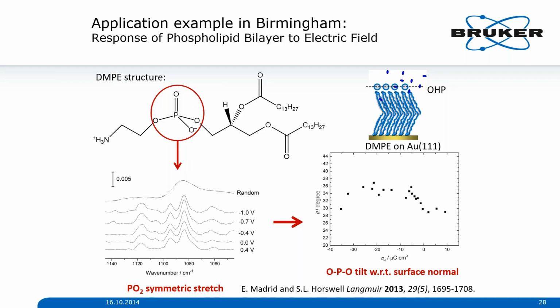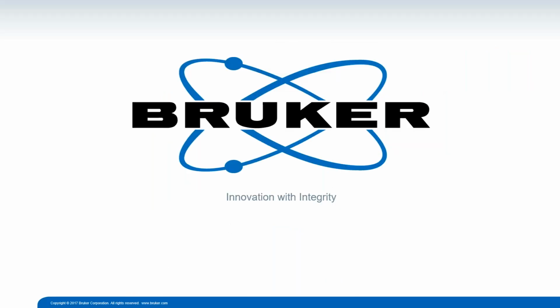And you can see from these publications that when you do these electrochemical studies, the tilt of molecules attached to the surface changes with changes of potential. So it's very interesting research for such applications. As you can see, spectroelectrochemistry gives you insight not only into what's going on chemically during the electrochemical reaction, but you can also learn how organized the layer is, what the tilt angle is, and many other applications can be explored from these studies. With this, I would like to finish and pass the presentation to the next colleague from Gamry.